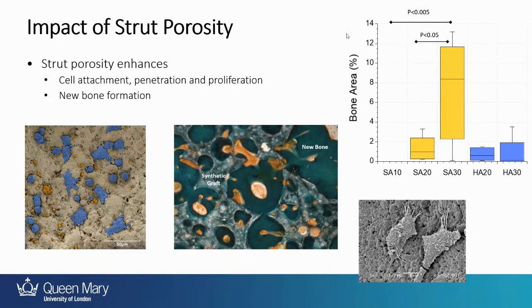What was really surprising to us, though, was the impact of strut porosity. So putting porosity into the struts of the material, which we thought were there mostly for nutrient control. We found that if you optimize the chemistry, so you use silicon HA as opposed to normal HA, and then put in different amounts of strut porosity, you could end up controlling your material to an extent it wasn't osteoconductive. So osteoconductive is where a material supports bone formation. It moved into osteoinductive, so you could implant it somewhere that there was no native bone, and you would get spontaneous bone formation occurring in the material because it's driving stem cells to differentiate down an osteogenic pathway.